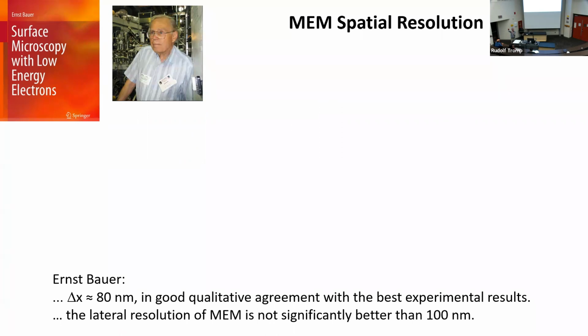But we can still see stuff on the sample. If the sample is rough, we'll see that. And in his book, Ernst writes, well, the spatial resolution is in the order of 80 nanometer, in good agreement with the best experimental results. And further on, he says the lateral resolution of mirror microscopy is not significantly better than 100 nanometers.